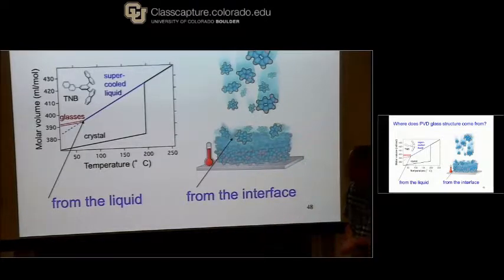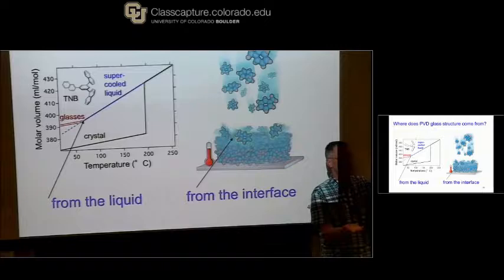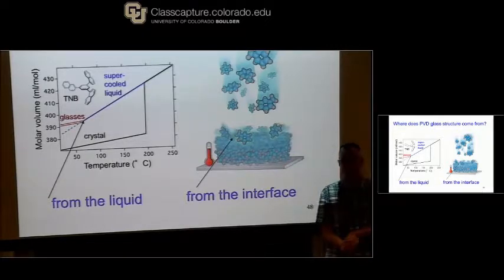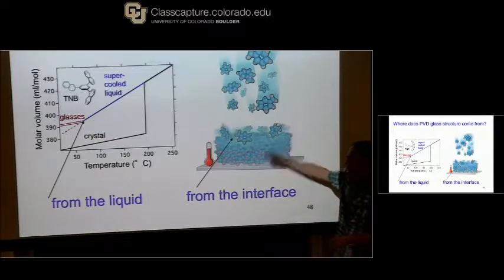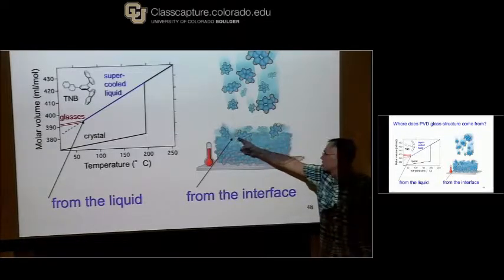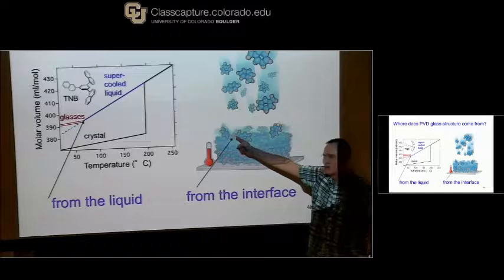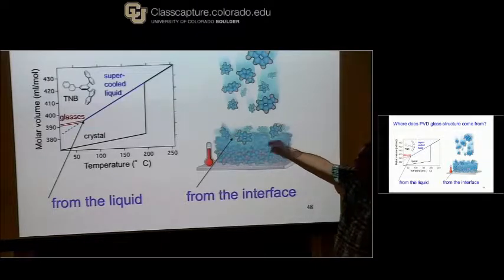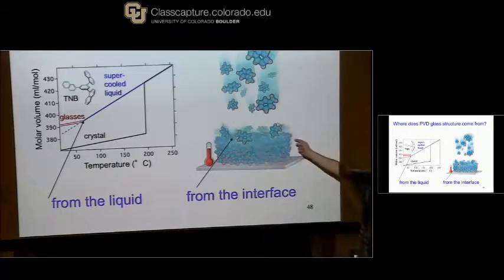Okay? So that would be my qualitative answer to the question of, in a liquid-cooled glass, where does the structure come from? Okay, well, we can't use that same answer for vapor-deposited glasses because they never see the liquid. They never see the equilibrium supercooled liquid. So my answer is the only place there's mobility in this glass is right here at this interface. And so whatever structure is in these materials is trapped in it based on what's accessible during the experiment and what's happening right at the interface. So now let me try and be more quantitative about this, but I just wanted to give you the idea first.